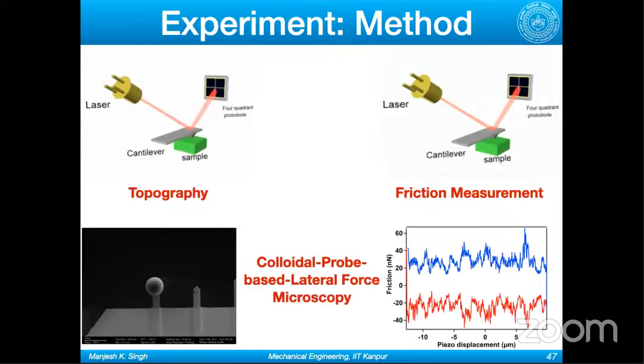You know what force you're applying because you know what voltage you applied. So you know the normal force, you know the friction force, and you can get the coefficient of friction from there. As I said, we use colloidal probe lateral force microscopy. I didn't use a cantilever with a sharp tip, because we are using polymers in our experiment. If you go with a very sharp tip of silicon carbide or something, it will simply scratch off your polymers. So you will not get to study what you want to see.